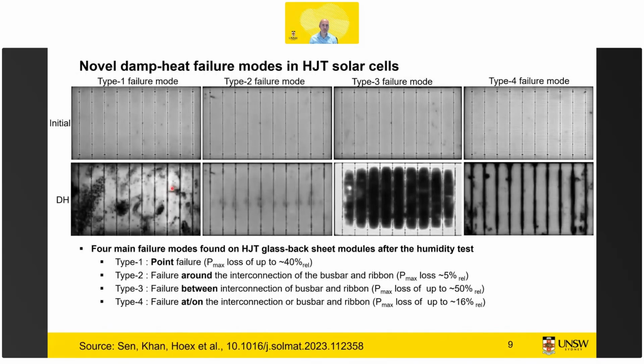So first of all, this is work we presented earlier. We published 3 years ago, where we identified new failure modes in heterojunction and TOPCon, but this is the first one, heterojunction, where we see that there's a number of corrosion-related defects that can lead to performance losses up to 50%. So it's really severe. So if we have this type 3 failure, and I will show the detail later what is the cause of this. And this is after 1,000 hours of damp heat. Then your PV module performance is too low to really move the needle.